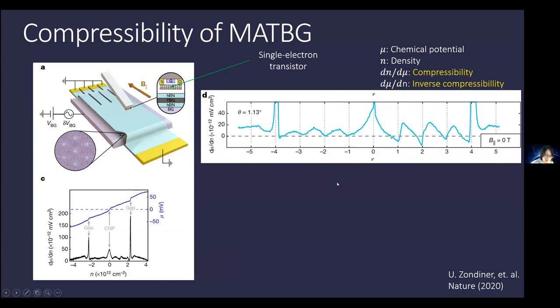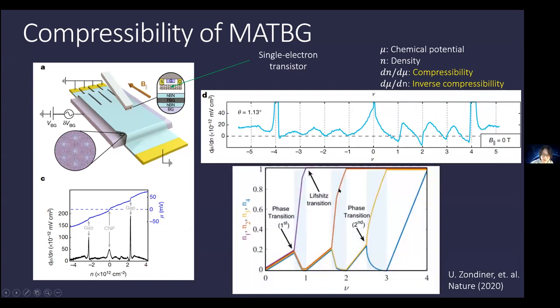These trends could be qualitatively explained by a model of spontaneous lifting of the spin and valley flavor symmetry inside the system due to enhanced Coulomb repulsion. One thing worth noting is that even in the nu = +/-1 state, where typically there are not many transport features at low temperature and zero magnetic field, there are still these bumps in the local compressibility measurement, which means that whatever phase transition takes place is already there, even at zero temperature and zero magnetic field.